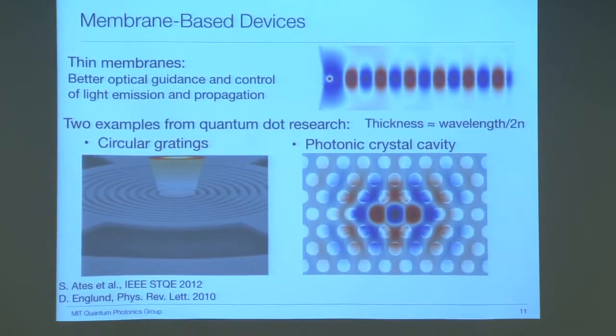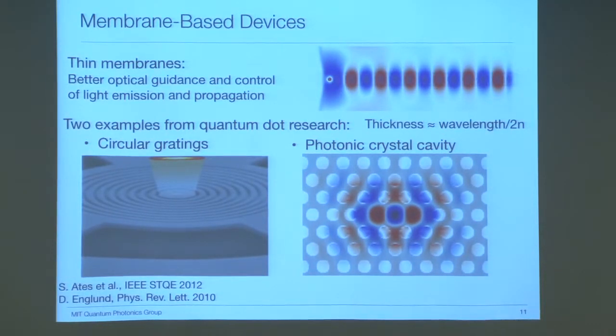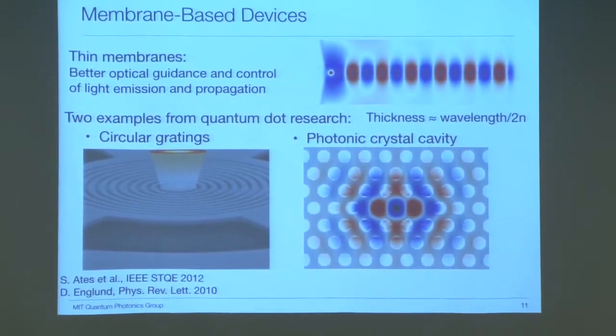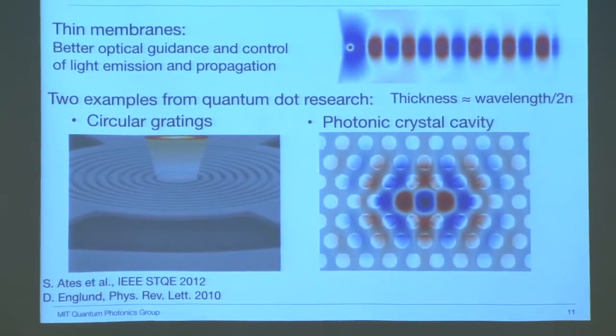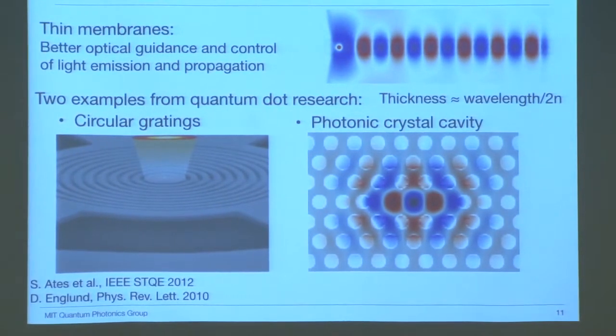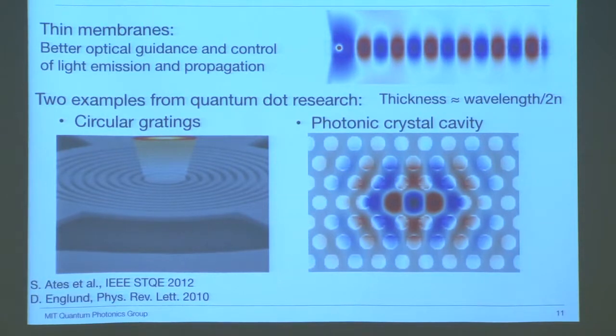Photonic crystal can confine the emission from a quantum dot in the vertical direction by total internal reflection, and in the horizontal direction by distributed Bragg reflection. And an additional defect inside of the photonic crystal at a quantum dot position would enhance the local density of electromagnetic states, and thus increase the spontaneous emission rate at a resonant mode.